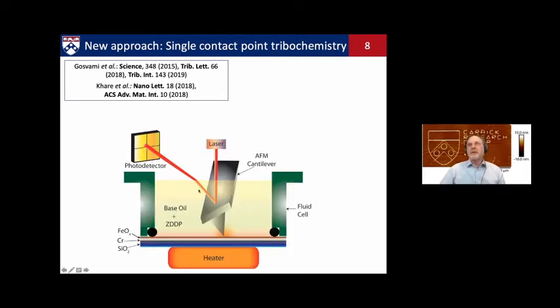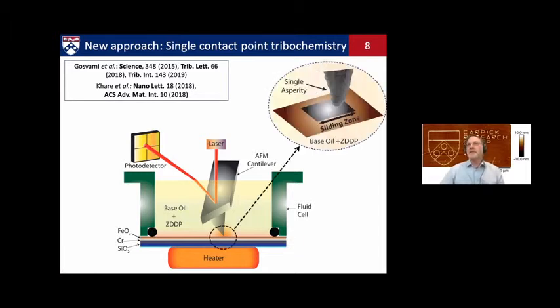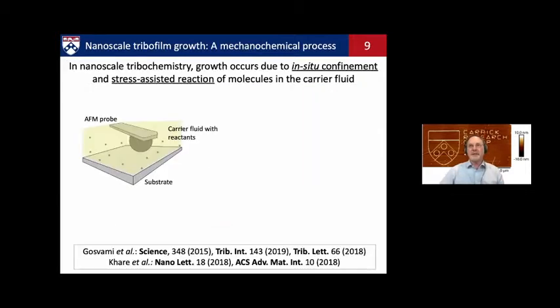So this approach that we introduced a few years ago now involves essentially using a fluid cell, or you can also use a film or even a droplet. You have your base oil, you have your additives like ZDDP in it. We have a heater in our AFM, and we use, say, iron or steel substrates. And you can run the AFM under this immersed condition with the additives present. You can slide in a confined zone to try to create your tribofilm or surface modification, and then you can zoom out and image it separately later.